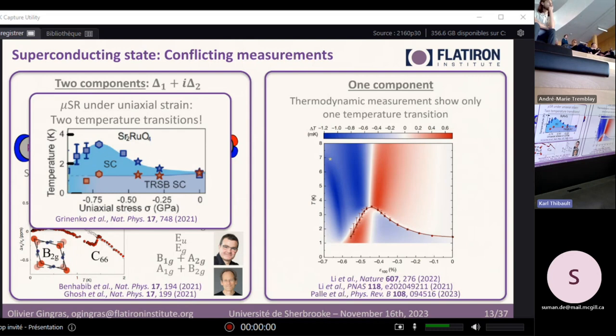What's the problem? The problem is that when you look at all the thermodynamic quantities, any thermodynamic measurement is actually much better explained by having a single component. And this is really strange because in general, thermodynamic measurements, in particular specific heat, or what I show here, the elastocaloric effect, are extremely sensitive to changes in the order parameter. And historically, they have highlighted hidden orders where any other method doesn't see anything, and they see that there's a second transition.